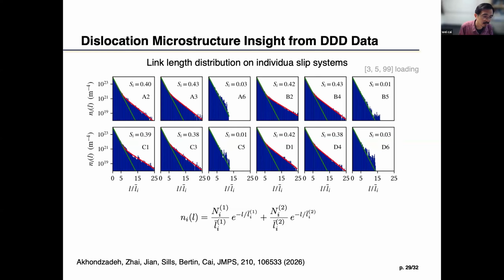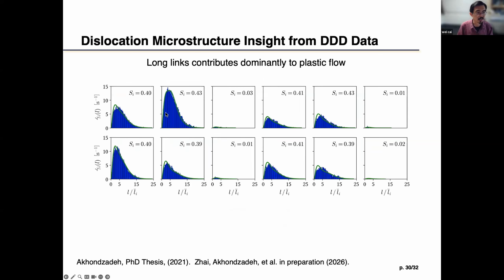And I think this is consistent with the notion that people usually think about mobile dislocations and immobile dislocations, but how do you characterize which one is mobile or immobile? Here you seem to say that the so-called mobile dislocations are very, very long links. They have this particular distribution, and if you integrate all of them, they contribute more than 50%, probably more like 70% of the plastic strain rate. So we need to pay attention to those very long links.